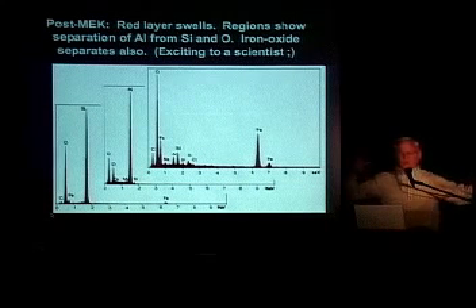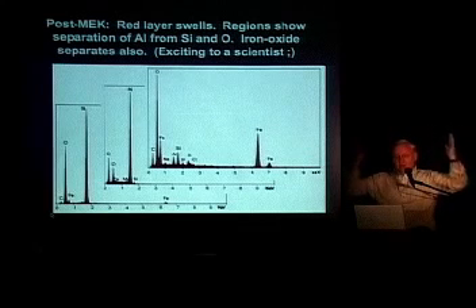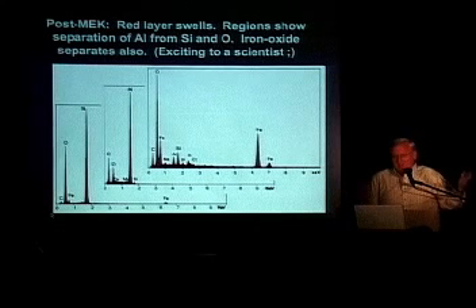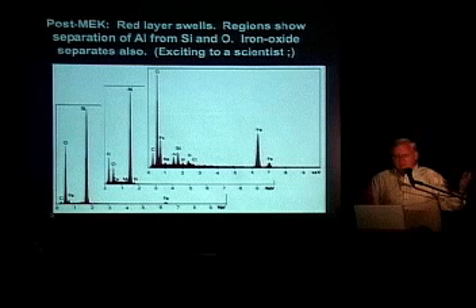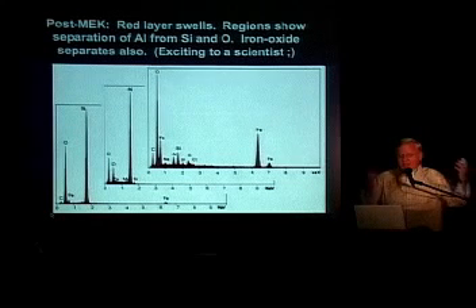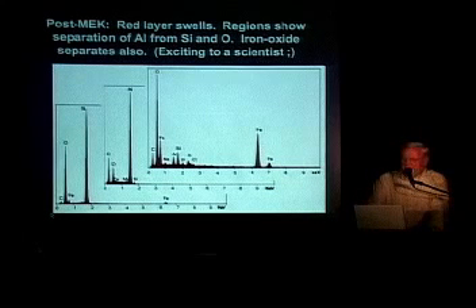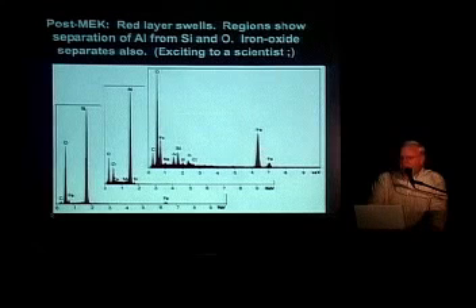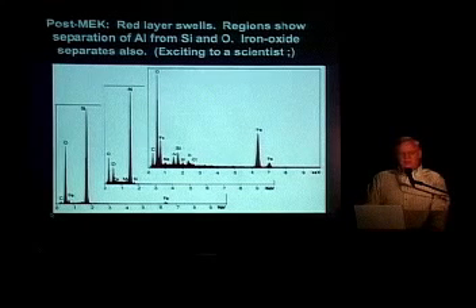You look at that and you say, whoa, there's aluminum in there, elemental aluminum. It's not aluminosilicate because the silicon's separate, and there's iron oxide. This is not just elemental iron. We didn't find any evidence of that in the red material.